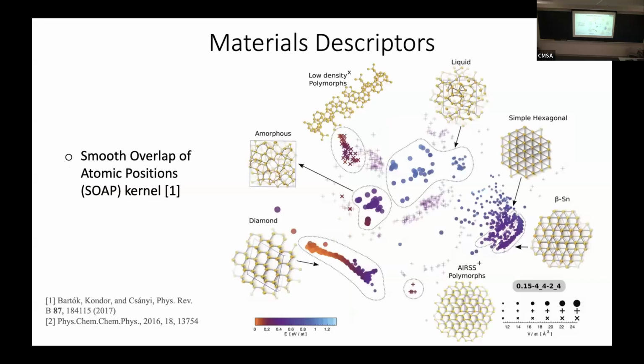Okay, so we have some data. Then we need some materials descriptor to describe our data before we can do any machine learning on it. And the descriptor I chose for this study was the smooth overlap of atomic positions kernel, or SOAP. And SOAP, the way it works qualitatively, if you have a lattice of atoms, you go to a particular atom, a particular site, and you look at its chemical environment, and you create some vector of numbers by linking that site to its neighbors. Then you go to the next site and you repeat that. So you get a matrix of numbers which encode all the sites and their chemical environments.